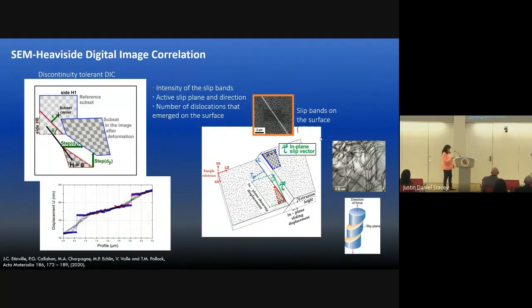Now I'll show you a few things that we've done using Heaviside digital image correlation. I think everyone knows what digital image correlation is. The only difference with the Heaviside is that it can detect a localization event and then split the problem apart and use a Heaviside analysis so that I can now know exactly how much slip happened in this band. And so regular DIC would give you these points, and the Heaviside would give you these. So I know exactly what the displacement is along the slip band, and then I can estimate the number of dislocations that passed by.